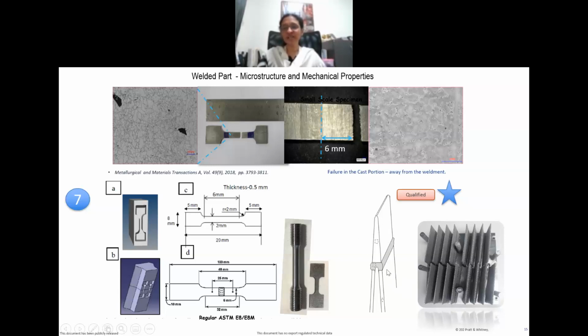One of the big challenges that we are looking at with researchers is how do we quantify small scale mechanical testing? Because typically we test bulk materials. This is the ASTM standard specimen, ASTM E8 or whatever. What is a big challenge in additive is we are making near net shape parts. So I can maybe get a small 2 millimeter mechanical test specimen without damaging the part, take it out. But at 2 millimeter or 1 millimeter, we don't have any acceptable test standards, isn't it?